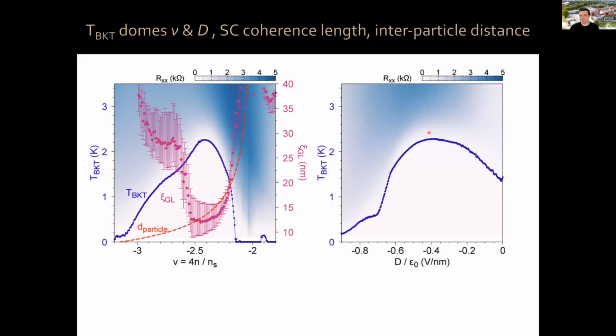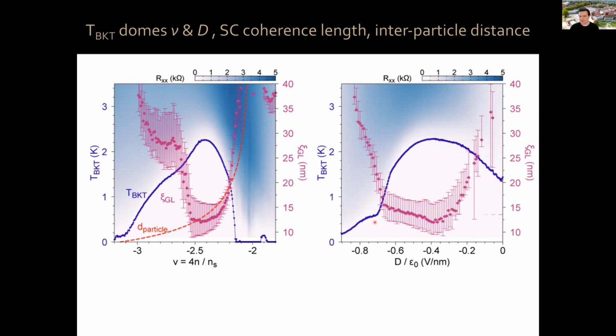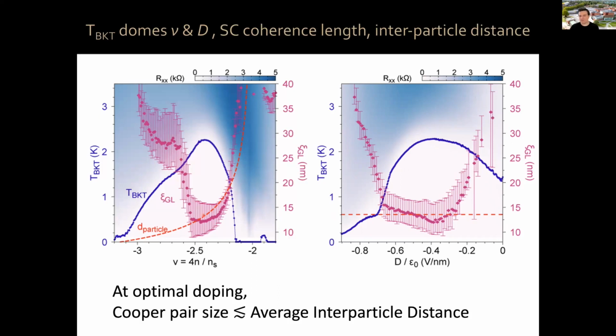You can repeat the same thing by looking at TBKT versus displacement field at optimal density, okay? You can also measure the superconducting coherence length, and this is the average interparticle distance at this optimal density, okay? As you can see, if you interpret the superconducting coherence length as the Cooper pair size, as you would typically do in the weak coupling BCS limit, your Cooper pair size is of the same order as the average interparticle distance at optimal conditions, okay? Now, of course, it's not obvious that you can interpret it once you reach this limit, but let's say it's clear that our Cooper pairs are tightly bound in the system.